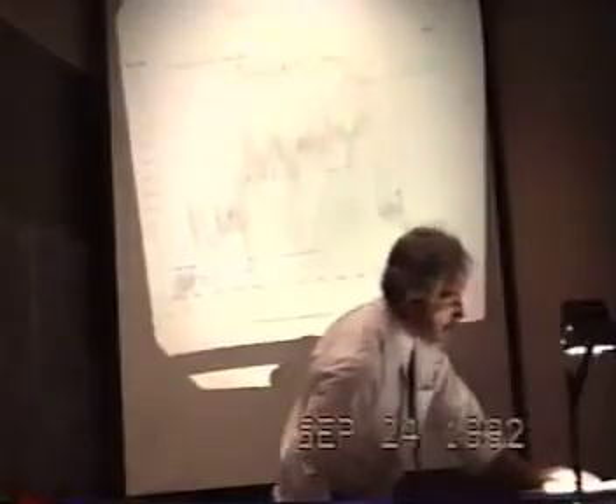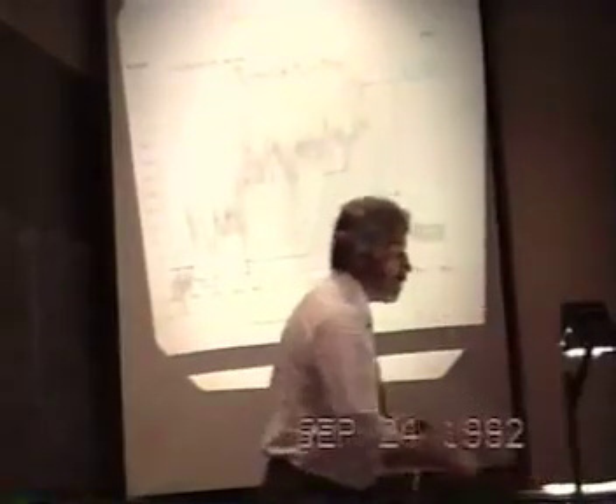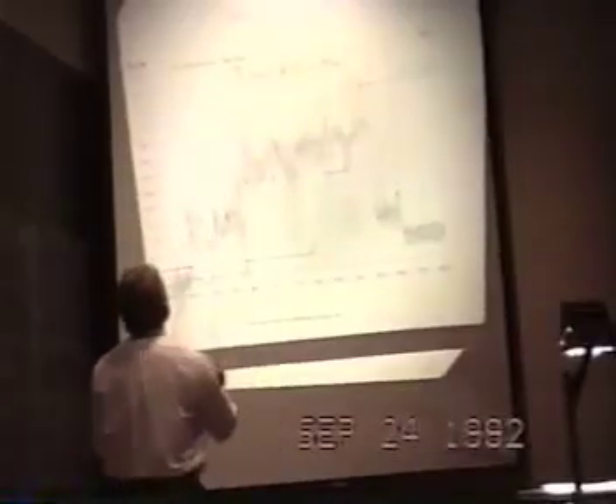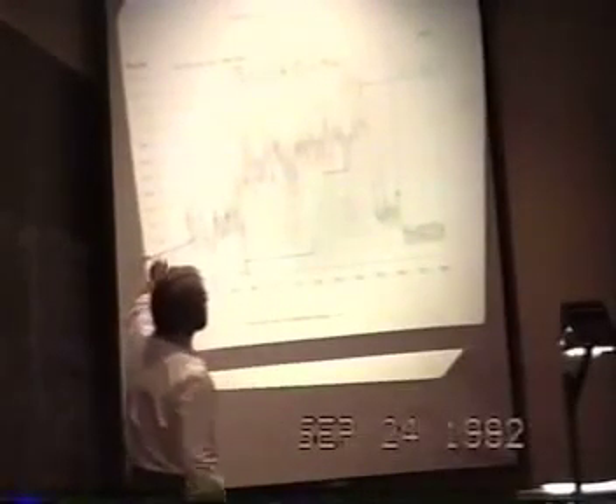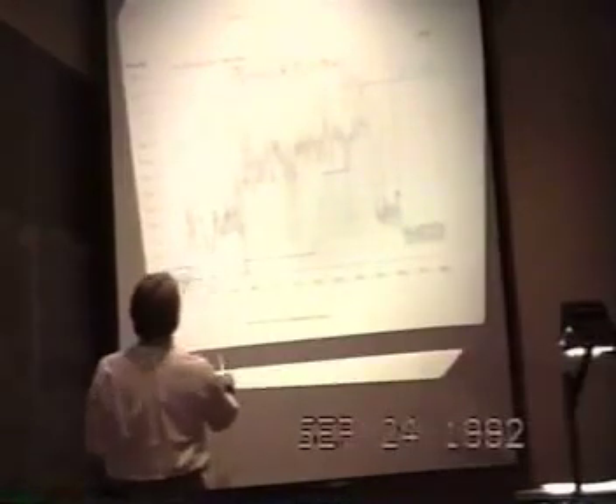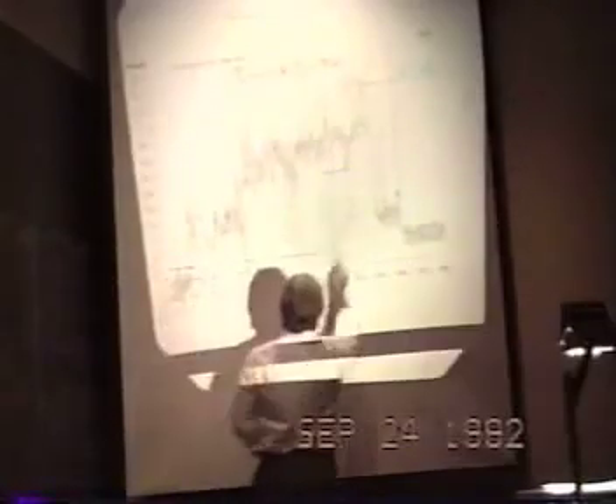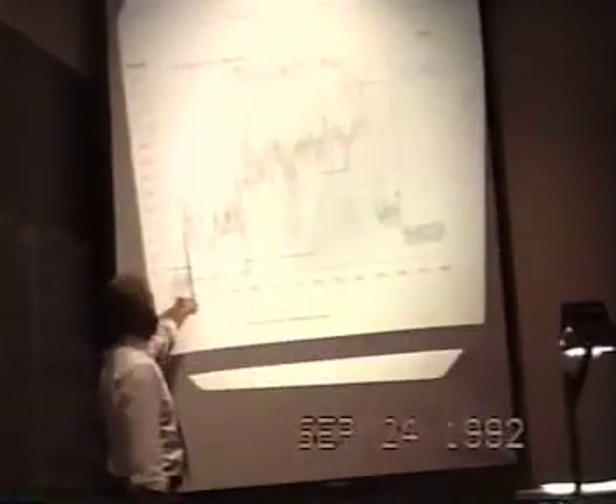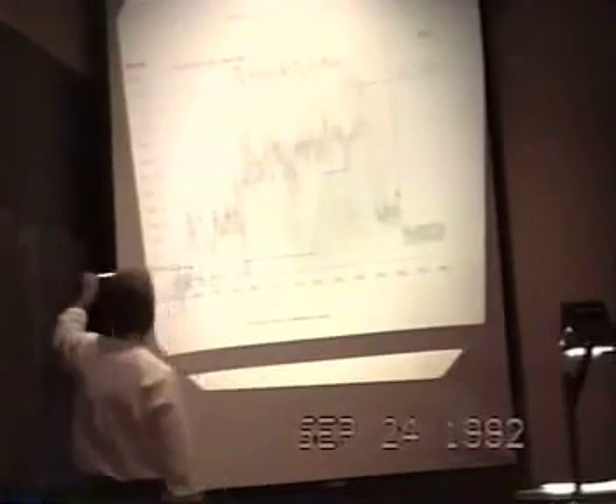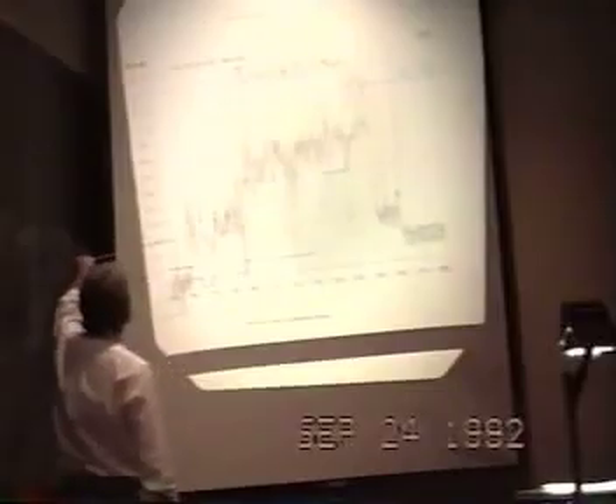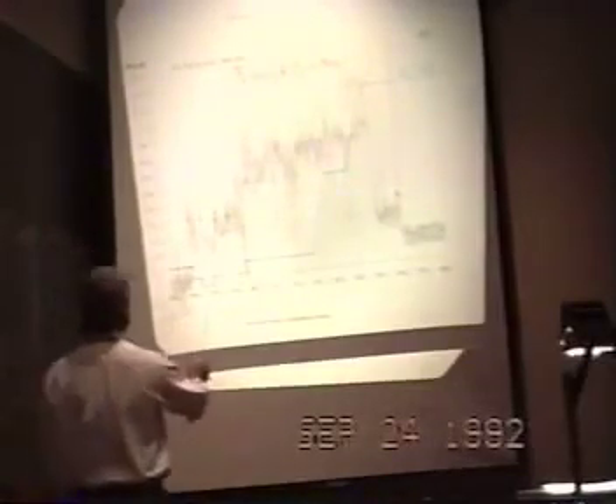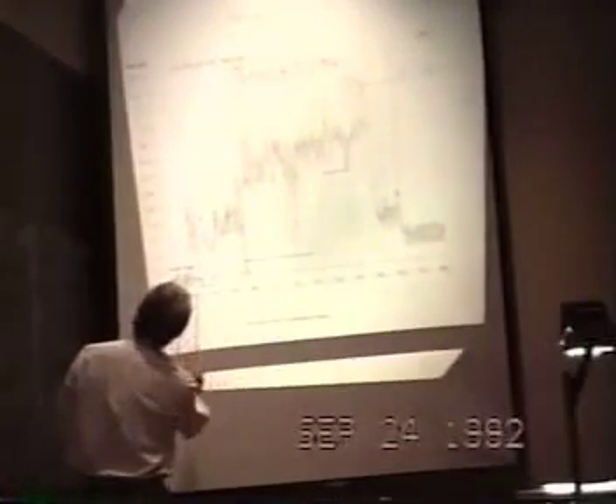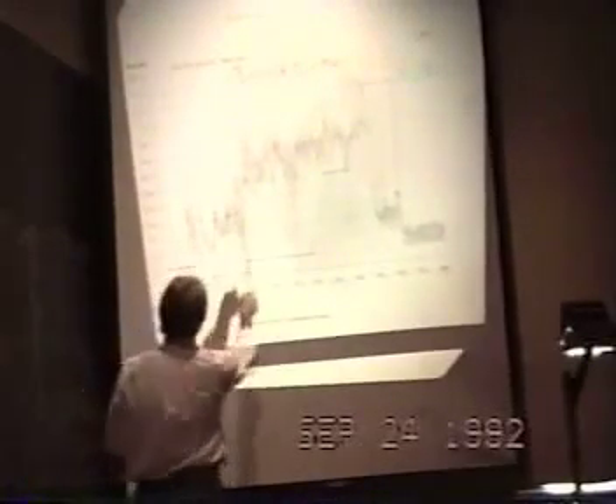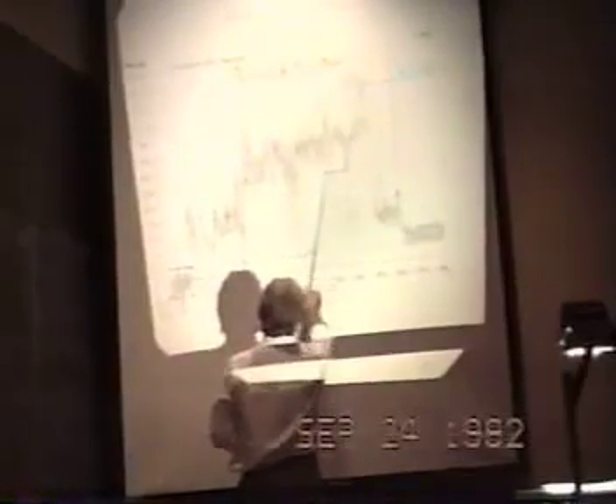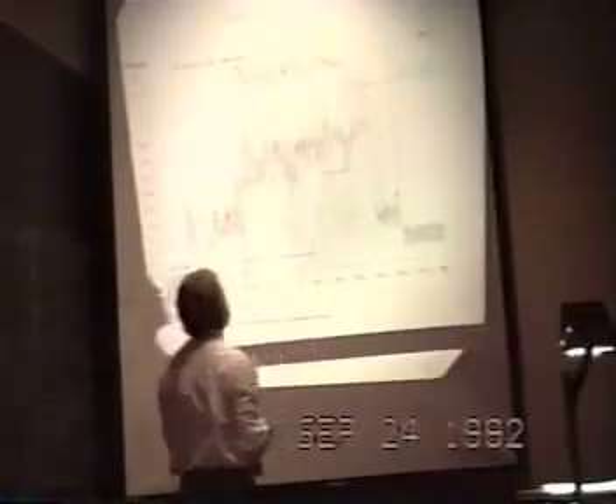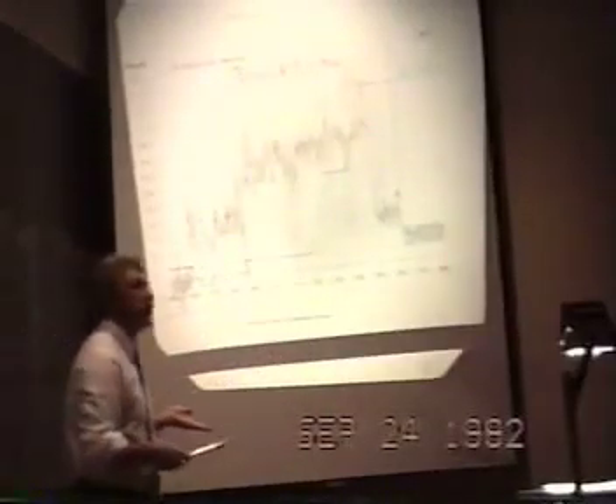More interesting still, perhaps, and here we show data for the raw measurements of two RTDs and two thermistors. This is the same current reversal that I showed you before, followed by a current ramp. The excess power, in fact, unbeknownst to us, had initiated at low current. We were starting to observe excess powers of the order of 0.3 to 0.4 watts before the current reversal. During the period of the stripping, the excess power actually comes back down towards 0, but restores itself. In an attempt to increase the excess power observation, we ramped the current, and the excess power is very little correlated to the current density in this case.